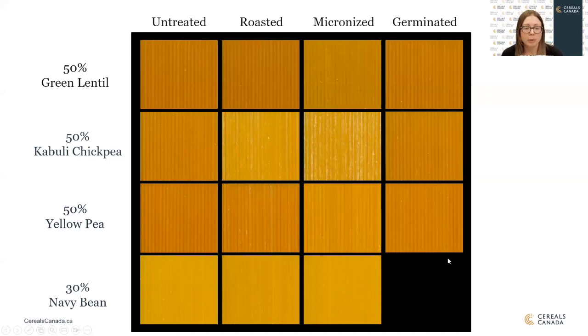The germinated flours look very comparable to the untreated, and they performed well in processing for this application as well. When we tried them, the eating texture was quite good. They were slightly less firm, which made them more desirable. Flavor-wise, the green lentil and yellow pea were better and more acceptable than the untreated, and they were actually the most preferred sample, while the chickpea still had some bad flavors associated with it.